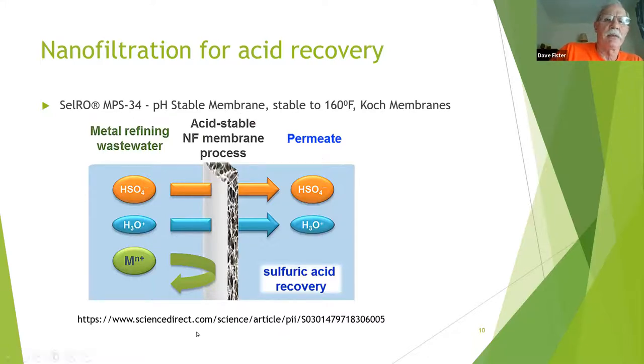Nanofiltration, and this is nanofiltration for acid recovery. This is relatively new. Again, Koch Membranes. For many, many years, any sort of osmotic membrane was not acid stable. So now they've come up with acid stable, in this case, nanofiltration membranes. This is also stable to 160 degrees Fahrenheit, which is impressive in itself.